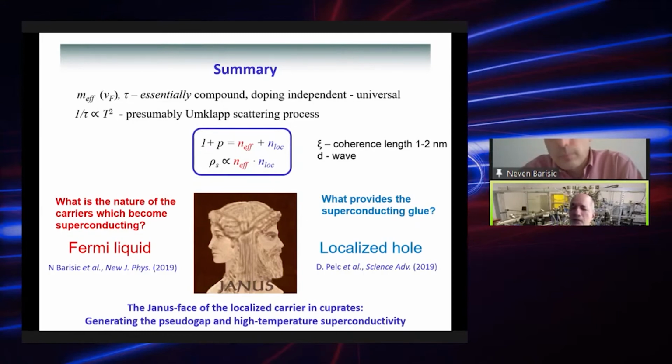So it is the opposite. I'm sorry I missed your talk yesterday because I was really in bed and being half dead. But I know what you're talking about. The thing is that this mechanism is everything in the unit cell and it's for very short times. So they couple two holes and then it's gone. In this sense, it cannot couple the whole fluid on the overdoped side. It will really correspond only to the number of localized holes, and that's it. It's not like Leggett would suggest, that for the phonon, a few of them make superconductivity and then the whole state becomes superconducting. It's really short range and a short-time glue.